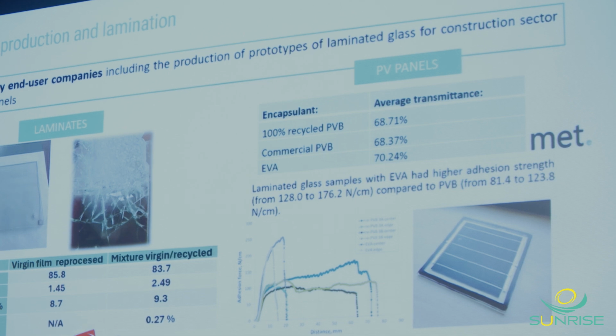But we would like to see in this comparison how the part of recycled PVB is affecting, decreasing or worsening these values, and what is due to the recycled material and the possible impurities, and what is due to the reprocessing itself of a polymer. Because when we make this virgin recycled mixture, we are reprocessing again the virgin PVB together with the recycled one. So this is the comparison that is here. And in terms of transmittance, of course, we are lower, and in terms of haze, we are a little bit higher. Also for yellowness, we are a little bit higher.